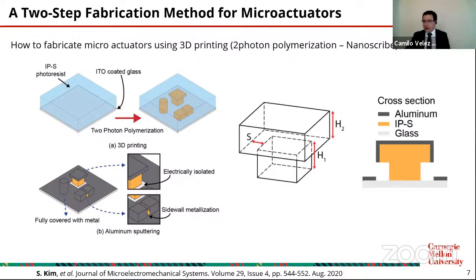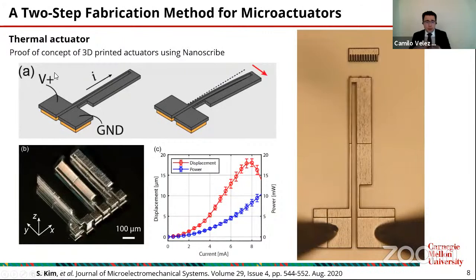And with this approach, we managed to create some thermal actuators. That's the first step into an actuator. You pass current through one of the beams. The beam is going to heat up more than the other one because of the aspect ratio of the shape, and this one is going to deform at a different rate than the bigger one. And by using this approach, we proved that we can make actuators with only 2 steps: only 3D printing, and afterwards sputtering of a metal. We tested these devices, and we managed to actuate them up to 8,000 cycles. So those are reliable actuators that could be used for prototyping.